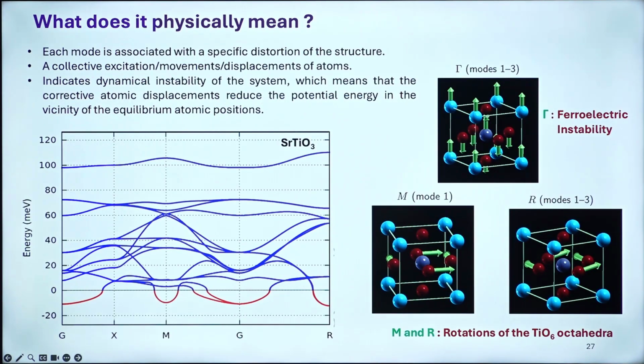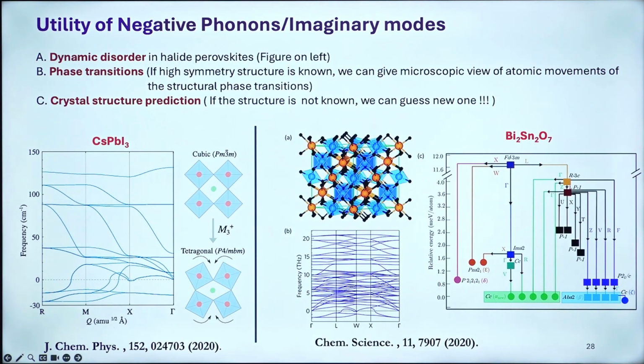Yeah, so this is very common in strontium titanate also, where we see gamma, then M, then it goes from gamma to R also. Modes 1 to 3 are ferroelectric instability at the gamma point, and M and R are the rotations of the TiO6 octahedra, which try to drive the system to ferroelectric by freezing these things. And this utility of these negative phonons or imaginary modes is also very common in halide perovskites,